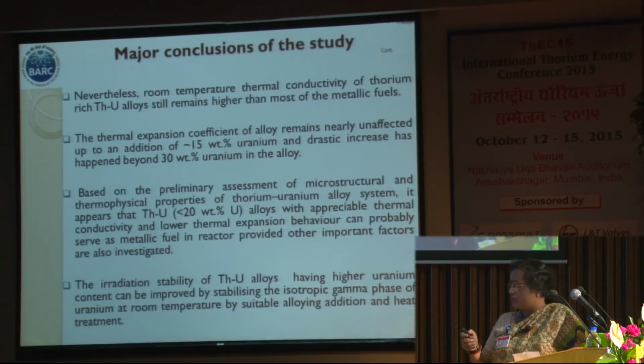Nevertheless, room temperature thermal conductivity of thorium-rich uranium alloy still remains higher than most of the metallic fuels. The thermal expansion coefficient of the alloy remains nearly unaffected up to an addition of 15 weight percent of uranium, and a drastic increase happens beyond 30% uranium in the alloy.